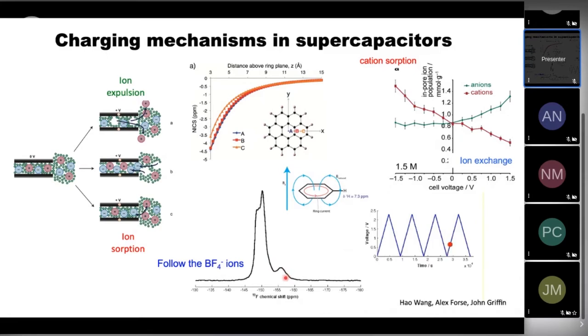So at 0 volts, they're negative, and then they shift to the left as you charge the material to positive voltages. And what you're seeing is the same phenomena that chemists are very used to in doing NMR of aromatic materials. So if you're an ion sitting on top of the sheets that are largely graphitic or graphene-like, you see the large ring currents that you would see in a benzene molecule.